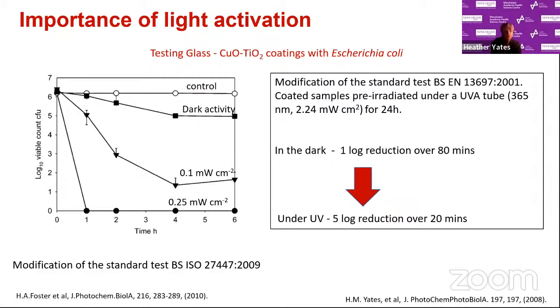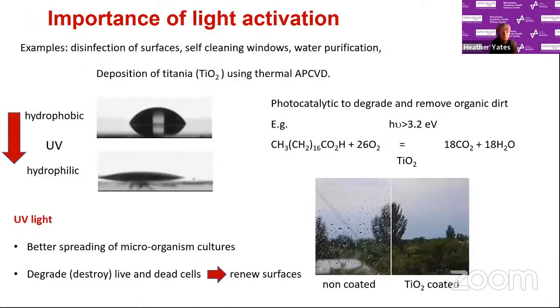You're getting a small amount of reduction and antimicrobial behavior, but just add a small amount, 0.1, 0.25 milliwatts per centimeter squared of UV light, and immediately you have a massive reduction in the cell count. So it's important that you can activate the surfaces under UV. Well, the importance of light activation.